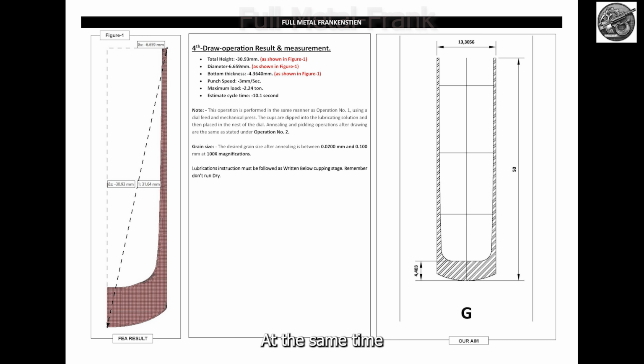At the same time, the outer diameter shrinks to 6.659 millimeters, the height is 30.93 millimeters, yet the bottom thickness stays solid at 4.364 millimeters, just where we want it. This stability at the base ensures strength while the walls and diameter continue to adjust.